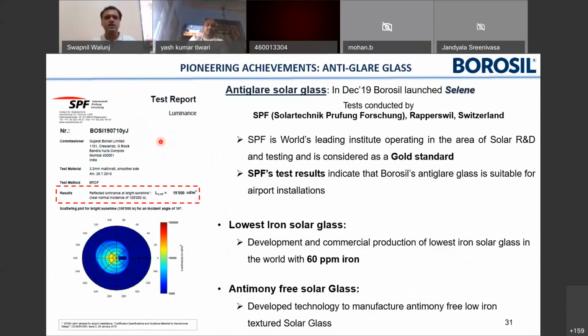testing agency, SPF. They have certified that for this anti-glare glass, the reflective luminance should be lower than 20,000. We have been able to get this reflective luminance to lower than 20,000, that is 19,000. We are well within the limits. SPF is considered to be the gold standard in testing.